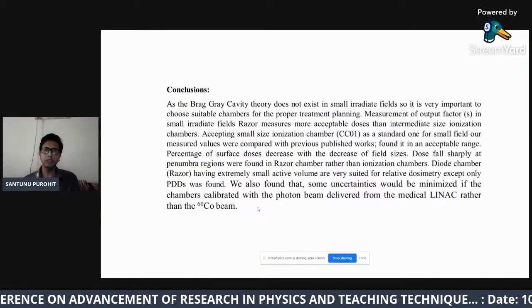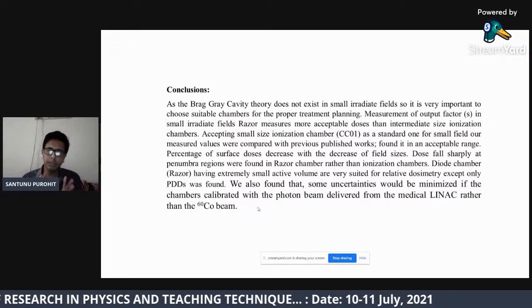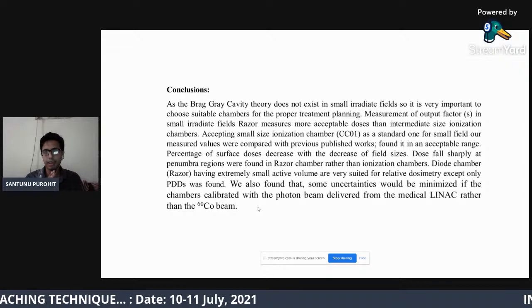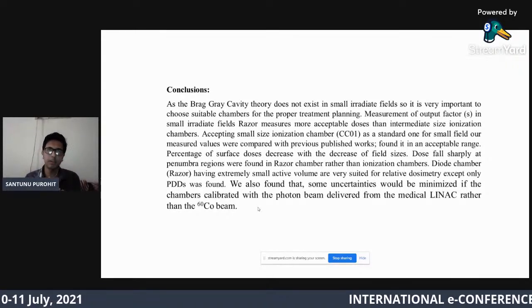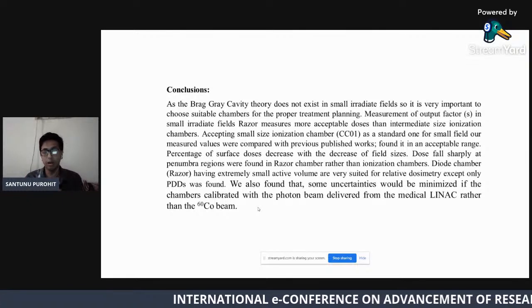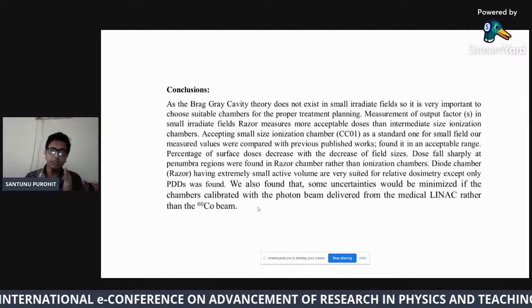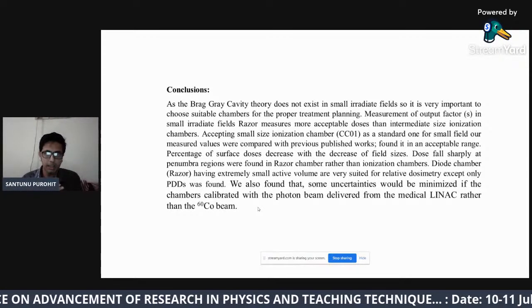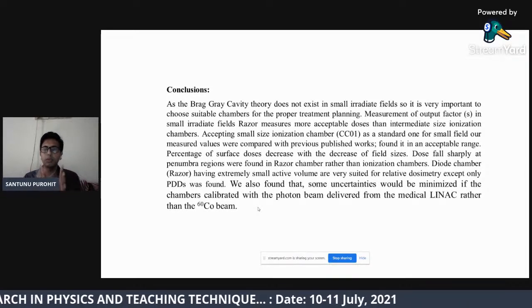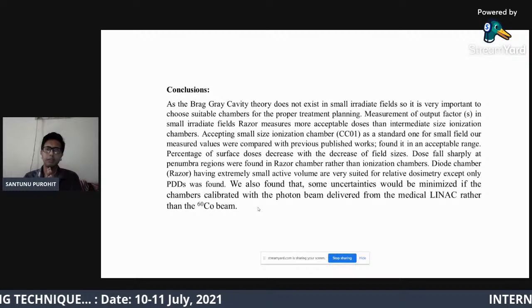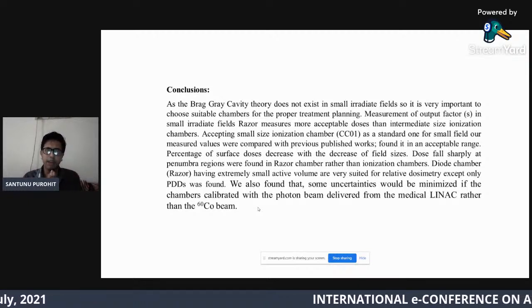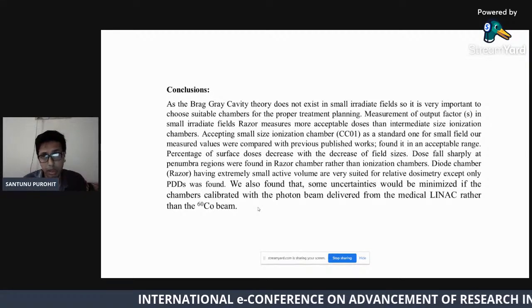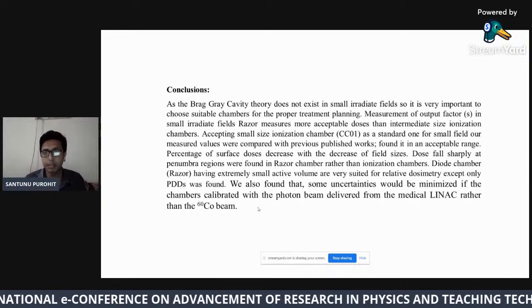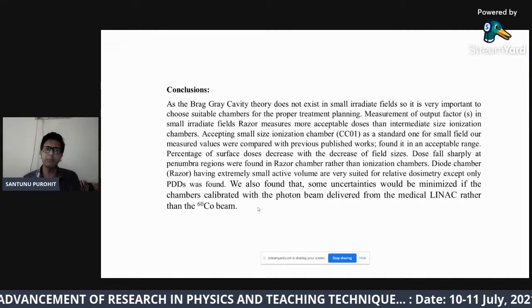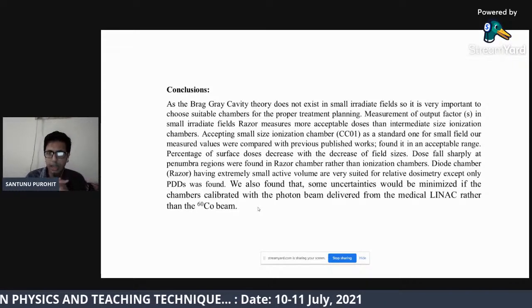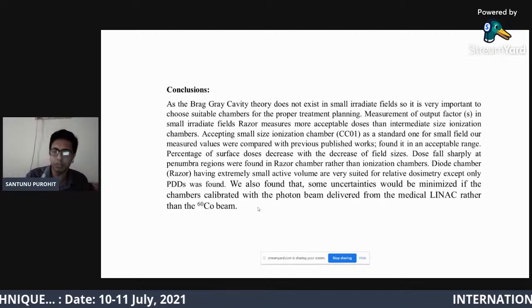And finally, if I conclude my overall scenario, if we use radiation therapy in small irradiated fields, not only for IMRT, IGRT, cancer therapy patients or tumor patients, but also if we use this type of technique for COVID patients, and if we maintain complete dosimetry technique for small field relative dosimetry, we found that the razor chamber has completely acceptable doses for the penumbral region. But if we think about percentage depth dose measuring with this type of chamber, it is not good enough because accumulation of dose is found.